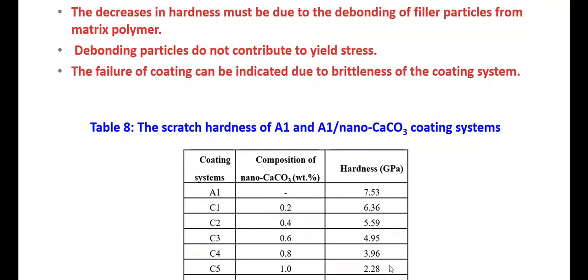So from here, we can see that the decrease in hardness must be due to the debonding of filler particles from the matrix polymer, and the debonding of particles does not contribute to yield stress. The failure of the coating can be indicated due to the brittleness of the coating system due to the high cross linking. Okay, so you can see what we call the hardness. The hardness reduces as the composition of calcium carbonate particles increases.